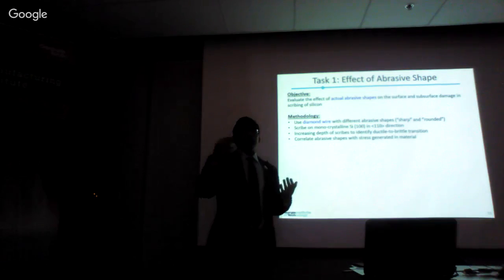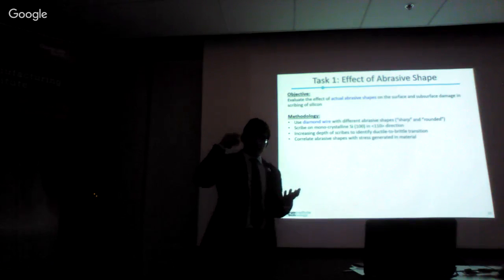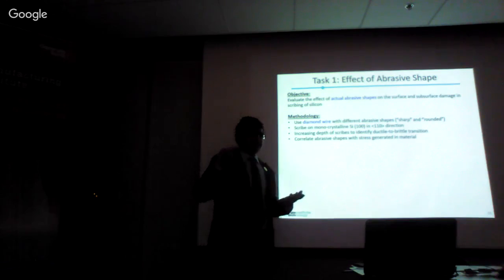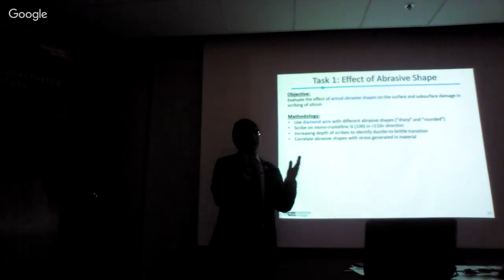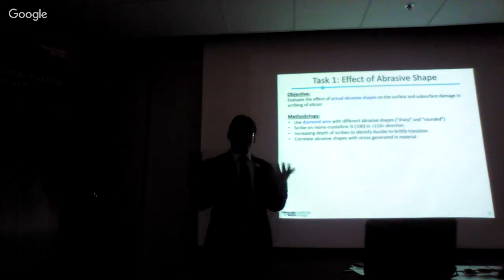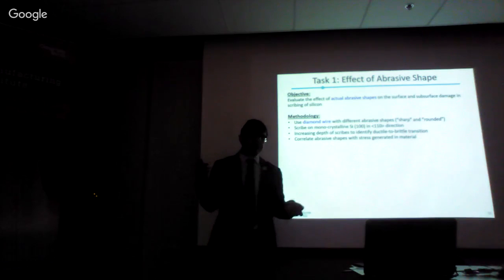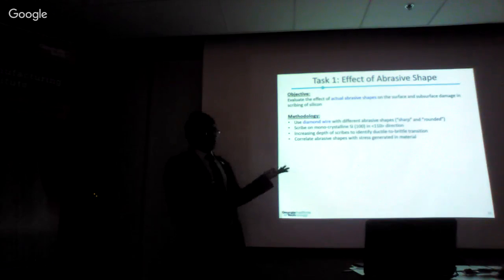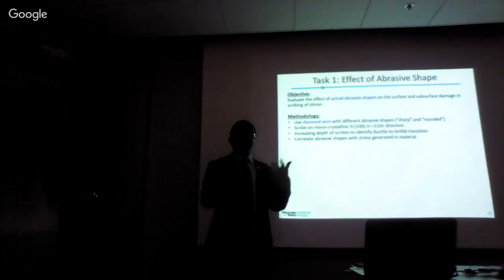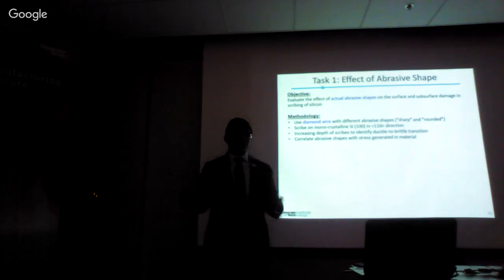And we can see the ductile to brittle transition as the abrasive or the wire goes deeper into silicon. And that is termed the critical depth of cut. We can compare the different shapes of the abrasives by comparing the different critical depths of cut, which is expected to come out of the scribing experiments. Finally, we correlate the shape of abrasive with the stress generated in the material. As I was speaking earlier, the different shape of abrasive is expected to create different stresses and hence a difference in ductile mode or brittle mode material removal.